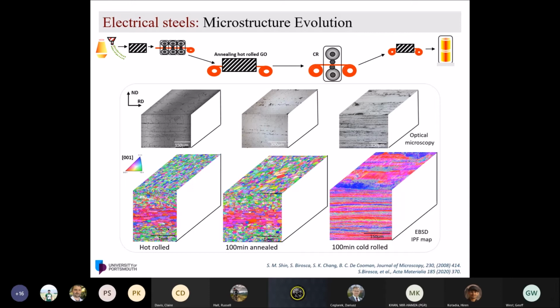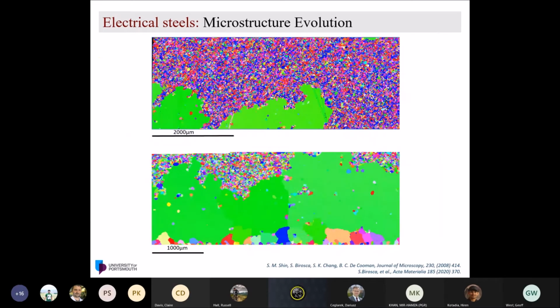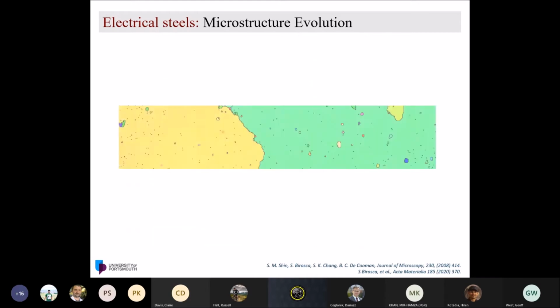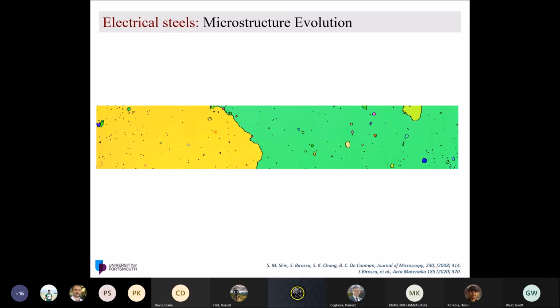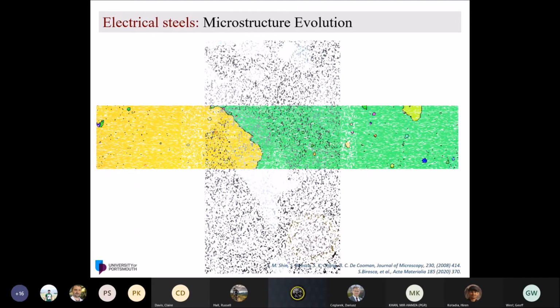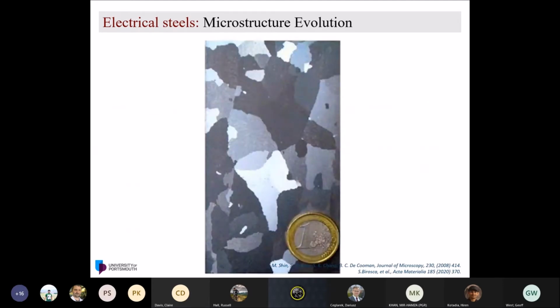So the microstructure is very complex, and we have to look at both surface and cross-section when we look at electrical steel thermomechanical processing. As we go for cold rolling, we will develop alpha fiber and gamma fiber, and then after the secondary annealing, the Goss or probably cube will grow abnormally. This is the work by Ali Nadoum, my previous PhD student. And then it will occupy the entire sheet, which is just one or two or a few grains, and the surface microstructure contains very, very large Goss grains. That's exactly what we wanted.